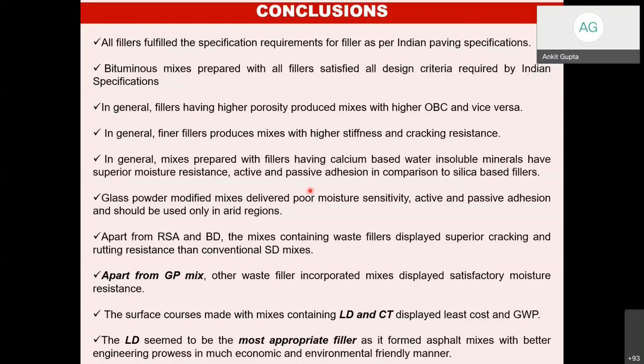So apart from the rice straw ash and the brick dust, the mixes containing waste fillers are displaying superior cracking and rutting resistance than the conventional stone dust mixes. And apart from the glass powder mix, all the other waste fillers are giving good results for moisture resistance. This is for the surface courses, because we have done the analysis only for the surface course. The mixes made with limestone dust and copper tailing are displaying the least cost and a lower global warming potential as compared to the conventional stone dust.